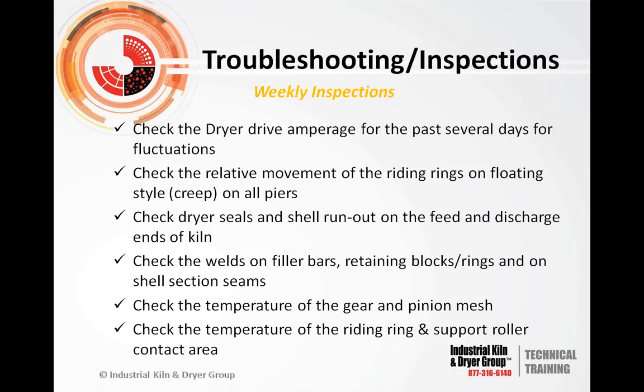If you get it where it spikes and goes from 90 degrees up to 110 degrees on the right side, your pinion and gear are not aligned properly, and you're going to have wear issues. So this is a real quick, easy check to make sure that you're maintaining a proper gear mesh and alignment of the gear. Also, if you start bottoming in the pinion, you're going to start increasing the temperatures. So it may have run 90 degrees on the pinion for weeks, and then down the road, all of a sudden, you're seeing spikes of 100, 110 degrees, and you've got some issues with heating up of the pinion.